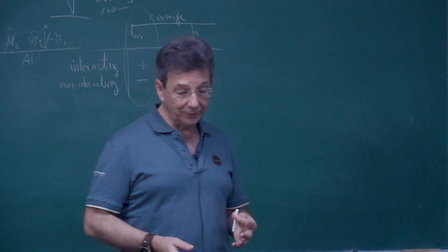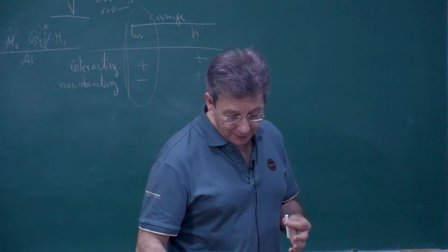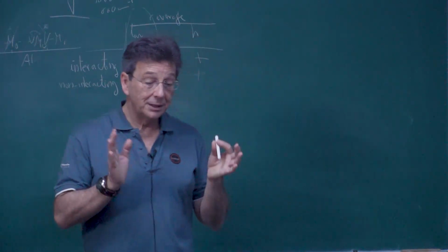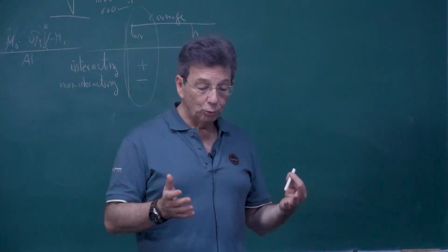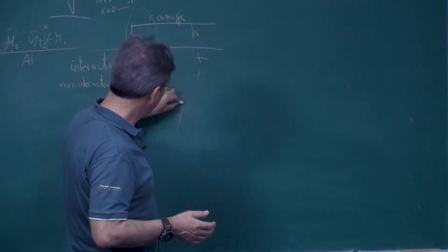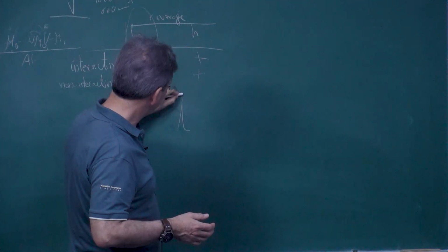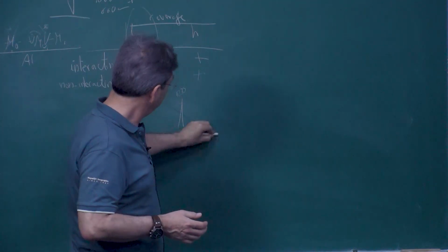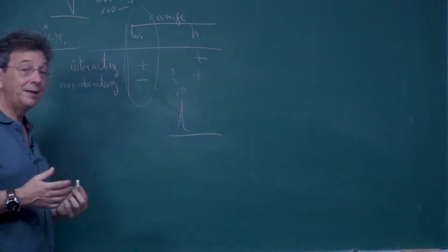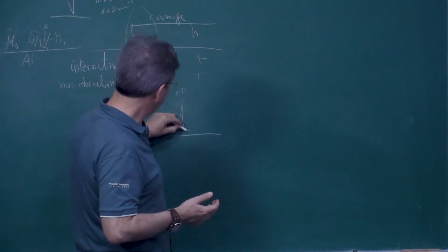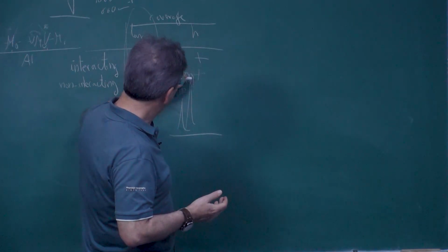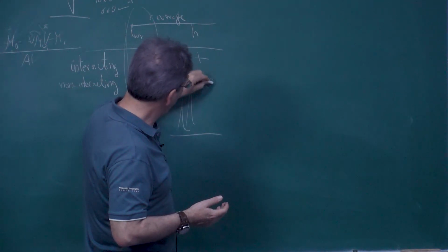And at the end, with the 5 weight %, you start to see new bands, like this one here, which already corresponds to crystalline vanadium pentoxide, but nanoparticles. Most of it will be dispersed vanadium. When you are looking at the supported vanadium, and you see a Raman band at about 1030, this is the vanadyl mode, and this is dispersed vanadium. When you start to see vanadium crystals, very suddenly you see a sharp band at about 990. This corresponds to crystalline V2O5.